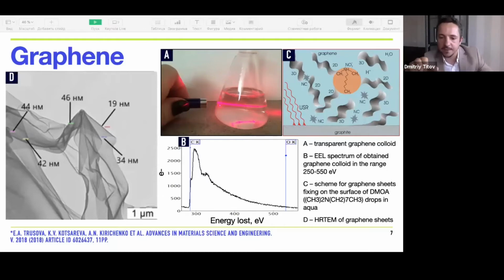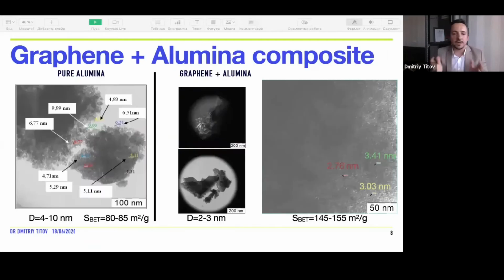Figure C describes the mechanism of the formation of the graphene sheet and the fixation on the organic molecule surface. Well, and about the composite powders. From the left hand, you can see a pure alumina powder. The average size is 4 to 10 nanometers. The size of aluminum oxide crystallites incorporated into graphene sheets doesn't exceed 3 nanometers. The dark field picture suggests that the surface of the agglomerates is coated with 1 or 2 layers of graphene. The specific surface of the composite was 155, which is 1.5 times more than for the pure aluminum oxide.